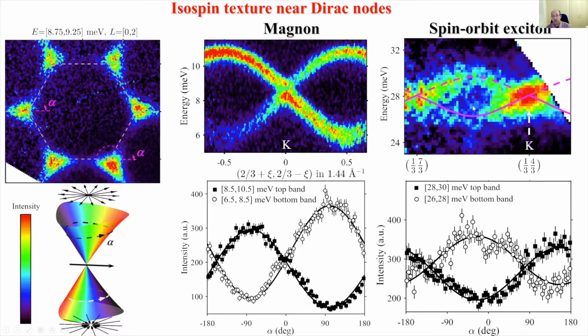sharpening of the spectrum down to resolution limited at the K points here and there, and it's much broader in other places. And then we can do the same type of exercise by looking at the intensity distribution as a function of angle. And then we find an alternation between maximum, minimum, 180 degrees away, and in complete antiphase between the top and bottom bands of the excitons. And again, with an offset that's completely explained by the buckling of the honeycombs. So this isospin picture is actually quite universally describing both the intensity anomaly in the magnons and in the excitons.